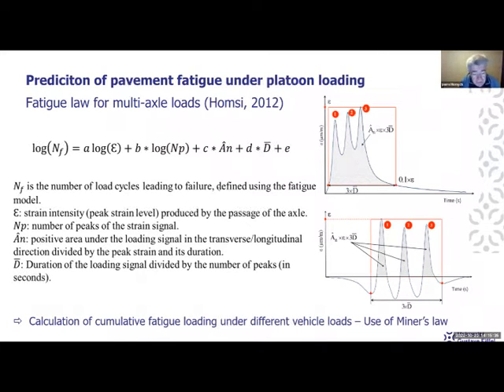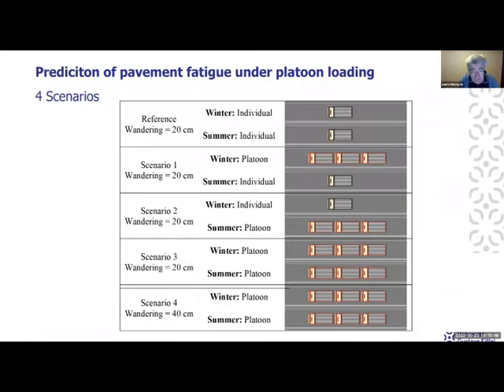And so we calibrated this model for the material which was used in the tests, and we tried to calculate the cumulative fatigue loading under platoons. And so we compared different scenarios. We compared a reference scenario with no platoon, only with individual trucks, and then 4 scenarios with platoons. In scenario 1, platoons were running only in the winter and individual trucks in the summer. Scenario 2 was the reverse, individual trucks in the winter and platoons in the summer, let's say half of the year during the cold period, half during the hot period.